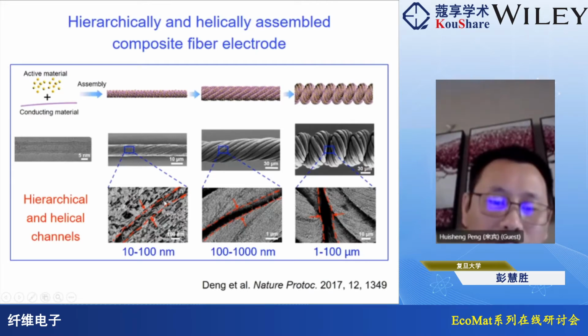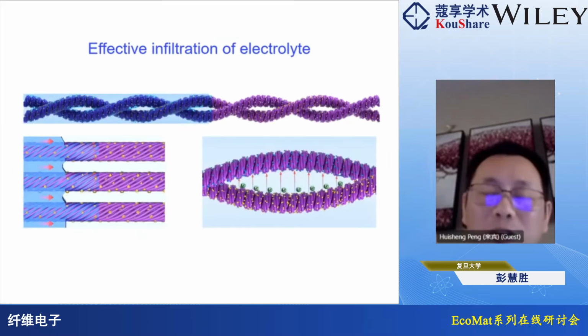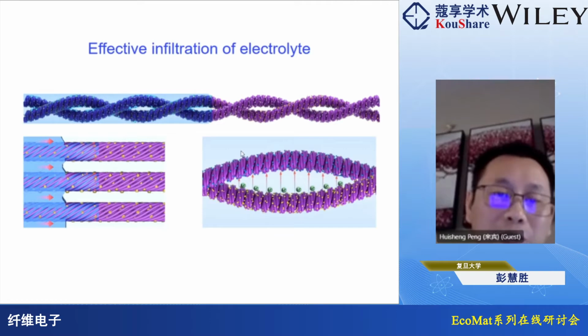So you will see that there are a lot of aligned channels: tens of nanometers between carbon nanotubes, tens to hundreds of nanometers between first-level fibers, and even these very large channels. So then we can have the required junctions to form this uniform electric field. And also, you can see that based on these multi-level channels, the electrolyte can be very efficiently transported, first through the larger pores, and then the smaller pores, and the tiny pores.